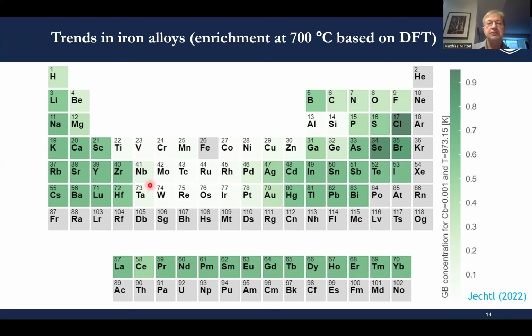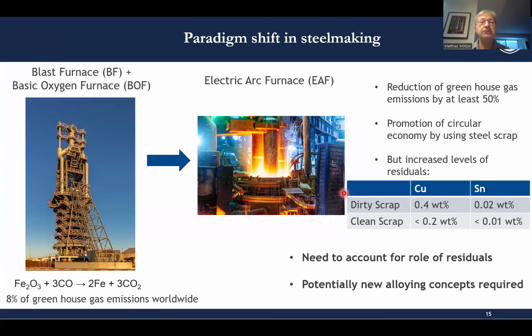And one can now use this maybe to consider which of these elements could be of interest for a new alloy design. But the other aspect that's important also is what impurities, what residuals could be of significance. And if you look here, this area, particularly with tin and antimony, bismuth, very strong segregants. And this becomes increasingly important with the current paradigm shift in steel making. So we have a change from blast furnace, basic oxygen furnace steel making to increasingly electric arc furnace steel making. And really the driving pressure is to reduce greenhouse gas emissions. And the steel industry contributes about 8% of greenhouse gas emissions worldwide. And if you look at the blast furnace BOF steel making route, that's really the production of carbon dioxide. And this is the major contribution to the greenhouse gas emissions from the steel industry.